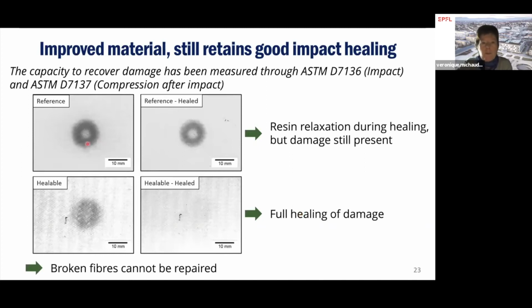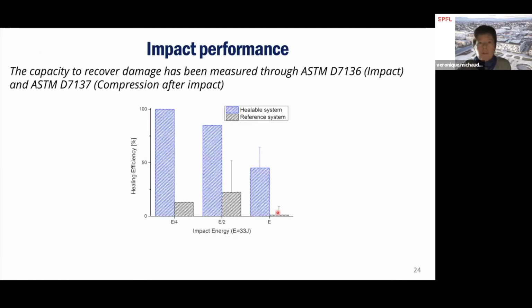So this is a reference epoxy as usual, and then the reference healed. We see a bit of resin relaxation, but the damage is still present. And in the healable composite, we have a full healing of damage. And then again, we checked it with compression after impact. And we saw that the healing efficiency of the healable system was very good, again, at low energy, quite good at a moderate impact energy, and quite decent at high impact energy.